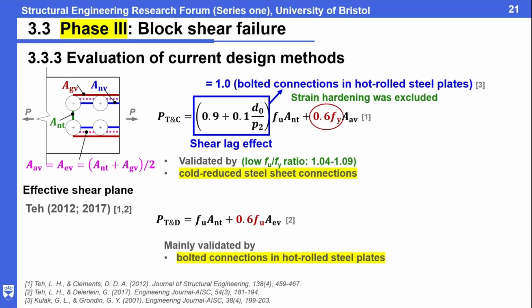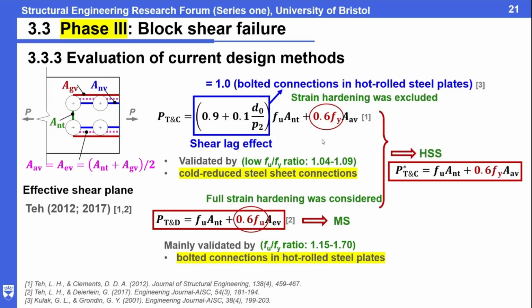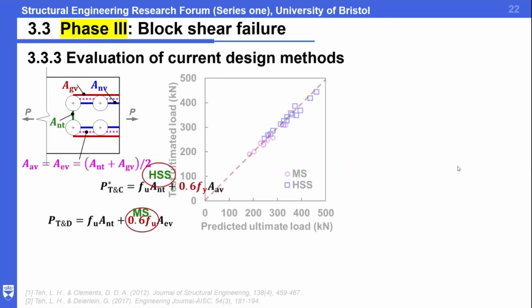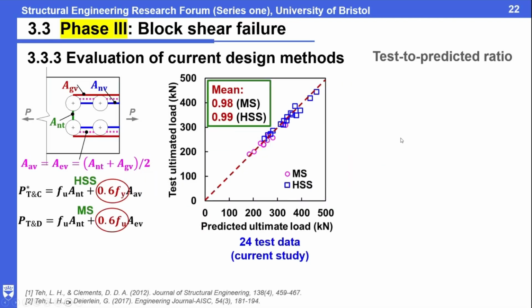These are the 2 equations from their paper. So let's see, based on our test data, whether these 2 design equations can be used. For the hot rolled, we will ignore the shear lag effect. So it will be simplified like this, these 2. This is for the mild steel fully, and this is for the high strength steel, ignoring the strain hardening. So let's see whether this one and this one are suitable for us. Based on our test data, we found that, okay, they predict very well. So that's done? No. The test data is not so large. We need to extend it a little bit.